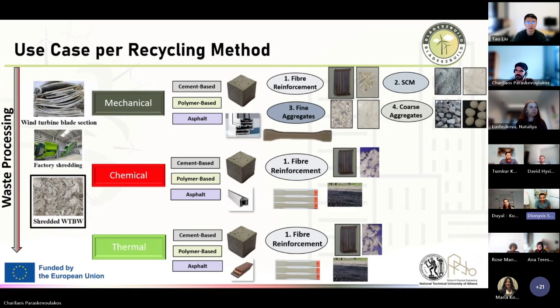On the last slide, I think you also mentioned a few things, but here are the different products and materials that we used and how we use them, from which recycling routes. So for the mechanical, from the chemical and the thermal, and on the right side of your slide, you can see, for example, as we use them as fiber reinforcement, or SCM, or fine aggregates, coarse aggregates. For the chemical and thermal, mostly as fiber reinforcement, since we can receive clean fibers, while for the mechanical, we get the full composite after this process. So we don't separate resin from the fiber like we do with the chemical and thermal, and that was the main difference among the 3 different methods.